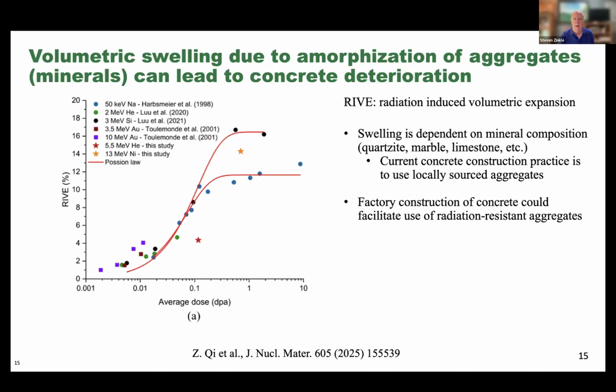Finally, I'll mention that there's potential applications for improved or advanced concrete systems. The degradation of a concrete that would be surrounding a nuclear reactor typically performs well for up to 40 years or so of operation. And then above that, some degradation has been observed in some nuclear reactors. In part, this is driven by radiation-induced volumetric expansion of the ceramic or mineral aggregates that are used in the construction of the concrete.